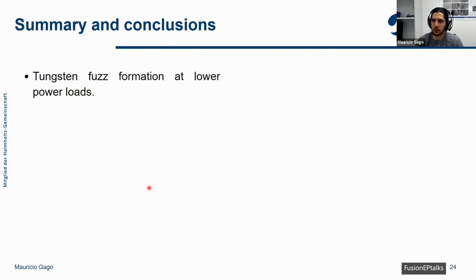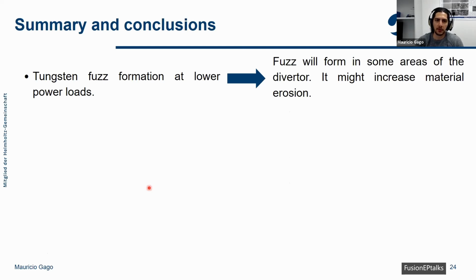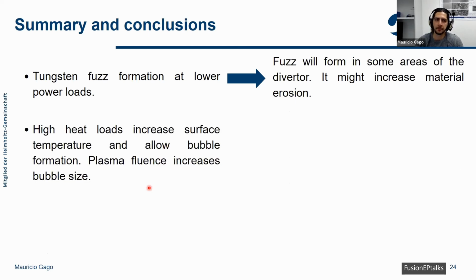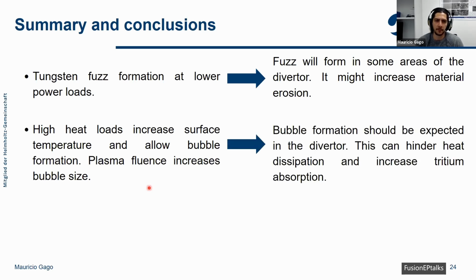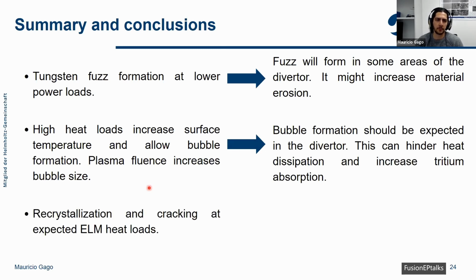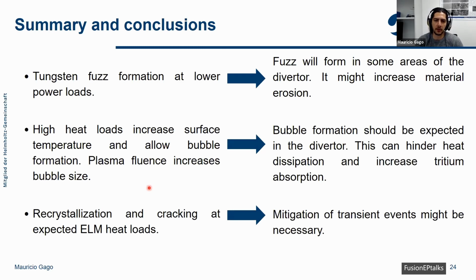So to conclude, we expect tungsten fuzz formation at lower power loads. This means that fuzz will form in some areas of the divertor, and it also might increase material erosion. Then high heat loads increase surface temperature and allow bubble formation, and plasma fluence increases bubble size. So bubble formation should be expected in the divertor. This can hinder heat dissipation and perhaps even increase tritium absorption. And then recrystallization and cracking at expected ELM heat loads is to be expected, and mitigation of transient events might be necessary.